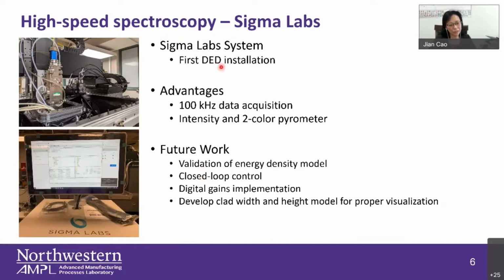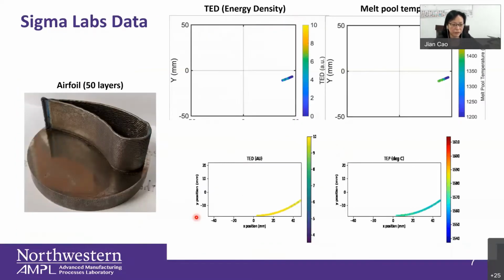Basically, when you look at the high-speed spectrometer, it has very high data acquisition. It's 100 kilohertz. And it can measure intensity, and also two-color pyrometer, so you can measure the true temperature. So here, for example, is a glance at what you can see. If you want to make an airfoil, you can see the intensity as well as the melt temperature measurement coming out from the top.